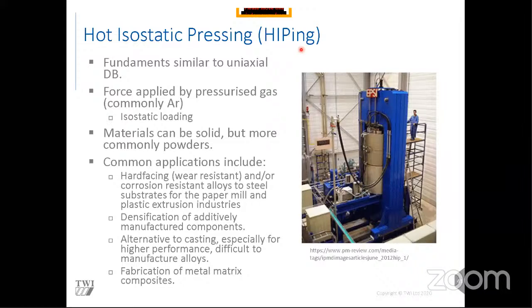This creates an isostatic load on your parts, meaning it's getting squashed from every single direction rather than just one. The pressures used are typically really high, up to 1,000 or 2,000 bar, which is why in the image you see an example of a HIP furnace. You've got your furnace here, and a massive yoke around the outside just to maintain the pressure inside the vessel - all of that is strength and reinforcement. So you can get some ridiculously high pressures.